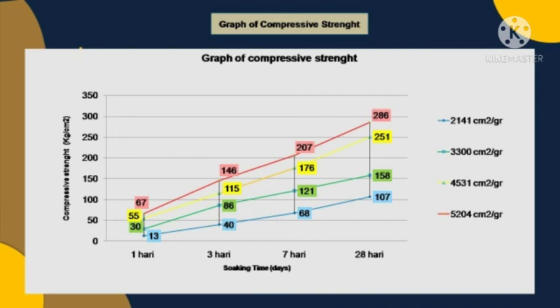From the graphical data obtained, there are 4 lines with different colors showing the value of fineness and test age against compressive strength. Namely, the blue line shows the compressive strength value against Blaine 2141, and the green line Blaine 3300. The yellow line with Blaine 4531 and the red one with a Blaine value of 5204 square centimeters per gram. From each Blaine value, at a certain age, the graph increases.